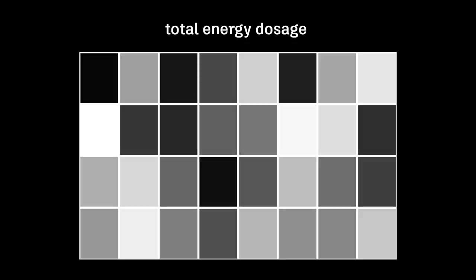The slice images create a panel of 32 rectangles where each rectangle receives a distinct amount of light energy. The rectangle that is illuminated in every slice receives 32 times the energy as a rectangle that is only illuminated in the first slice.